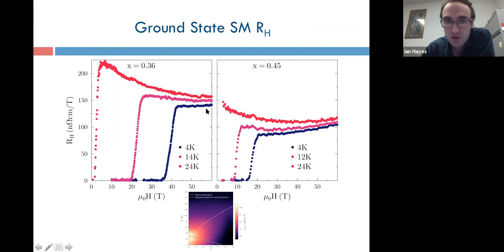So you can see it's a little bit stronger for the 36%, whereas at 50 Kelvin, you're already moving into the H squared regime for the 45% doped. In each case, there is still a bit of decrease that you can observe.